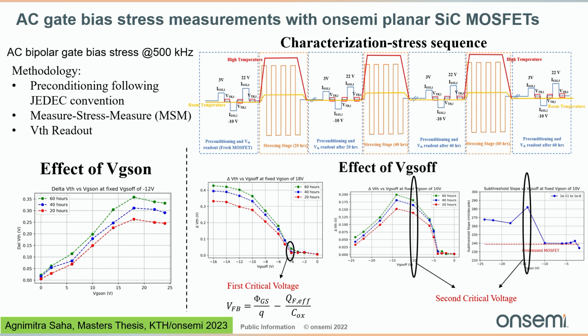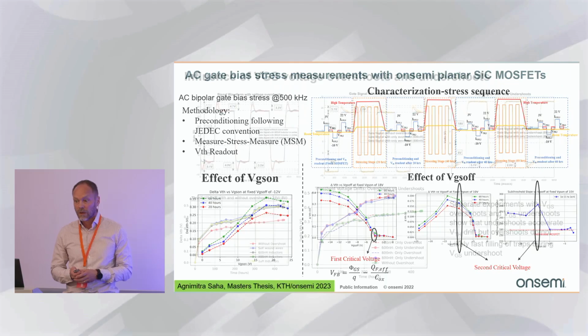But when you go further negative on this onsemi planar MOSFET, you start to see more permanent shift. So for that reason, you can see datasheets for SiC MOSFETs also often have typical or proposed operation voltage minus 3 volt. And going even higher, then there can be a reduction in the shift again, but that's a peculiar effect. Important is to know that if you go too large negative VGS off, there is a risk for threshold voltage drift.